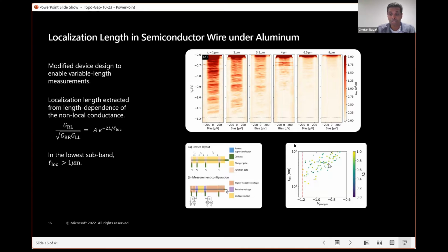And if we plot the localization length as a function of plunger gate, when we are at low plunger gates, somewhere around here, where we're in the lowest subband, the localization length is larger than a micron. It's a few microns. And we expect from simulations that the ideal clean system coherence length will be less than a micron. So we're in the happy regime where the localization length is longer. We expect the clean system coherence length to actually be about a third as large. So this is in a good limit in which the localization length is relatively large.